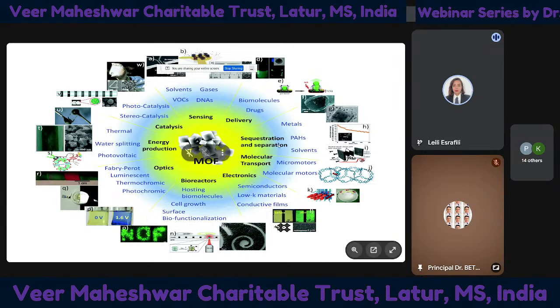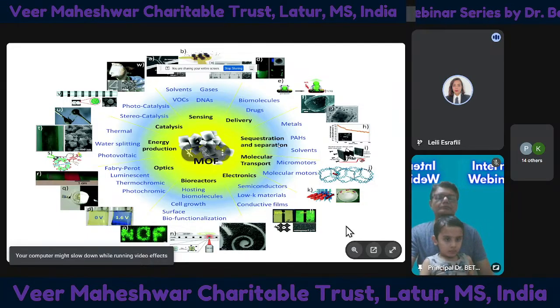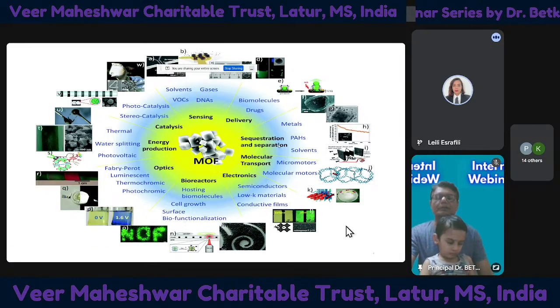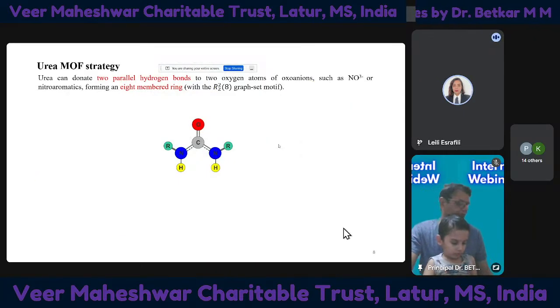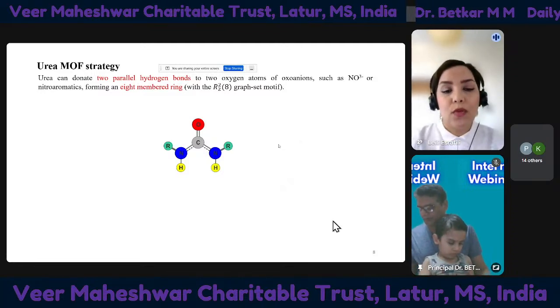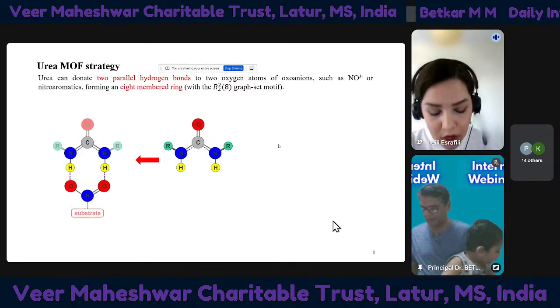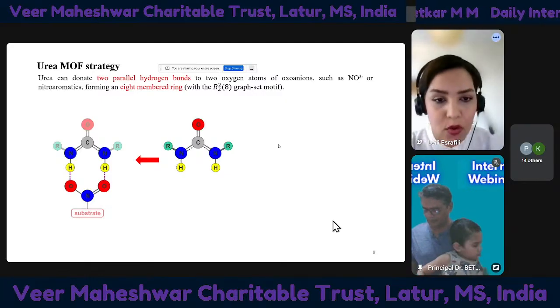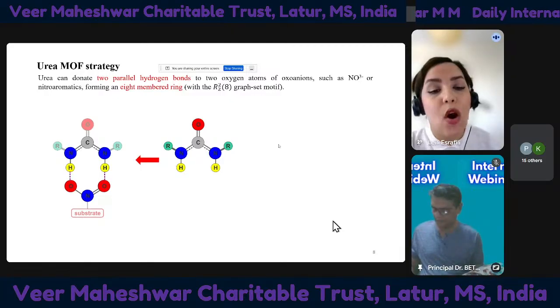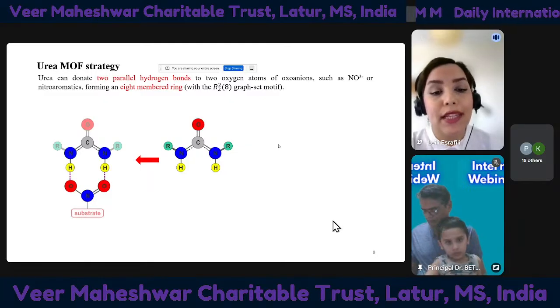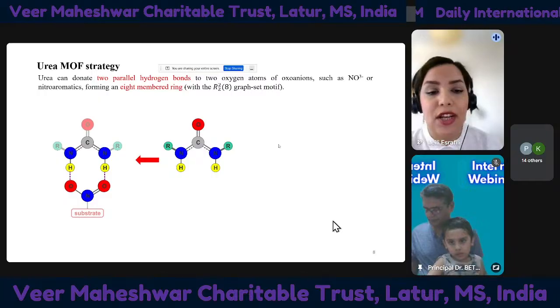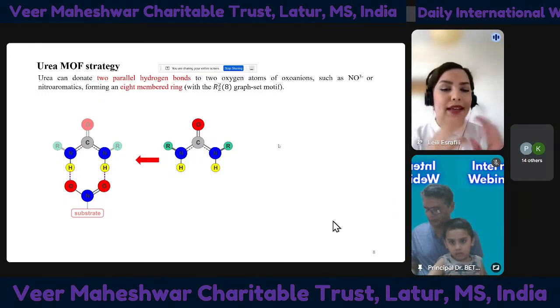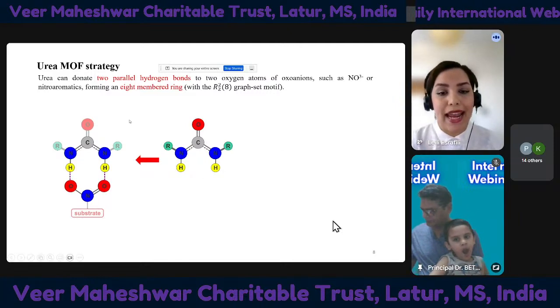In addition, MOFs have emerged as a promising material for heterogeneous catalysis, where the catalytic site can be incorporated directly into the framework or introduced later through post-synthetic modification, which is the focus of my research. And I want to start this catalytic activity and my research with the introduction of urea MOFs, or hydrogen bond donating MOFs. Urea is one of the hydrogen bond donating moieties; you can also have thiourea, squaramide, and so on. Urea groups are powerful hydrogen bond donors. Each urea unit can donate two parallel hydrogen bonds to electron-rich species such as oxoanions or nitro groups, forming, as you can see here, a stable eight-member ring.